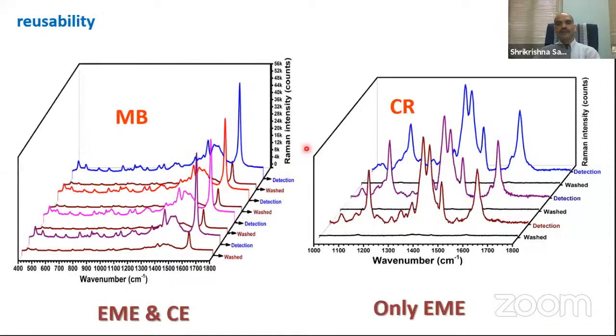Another thing is that people want to know, can I use the same SERS substrate repeatedly? Can I reuse it? It depends upon whether your molecule is chemisorbed or physisorbed. For example, this Congo red is another pollutant. When I wash it with water, I don't get any intensity. Then if I again put this probe molecule, I again get the intensity. Again I wash it, again I get it. So it means that there is only electromagnetic enhancement, there is no chemisorption.